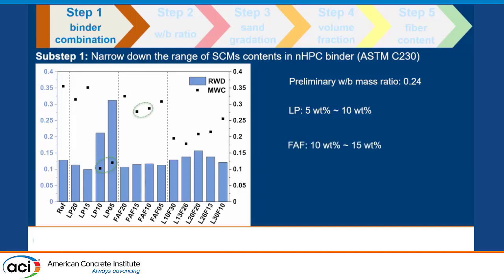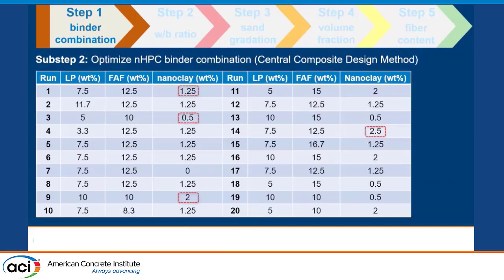Similarly, we can find the optimal range of Class F fly ash is 10 to 15%, and in the ternary binder system, the results confirm that the limestone powder content should be less than or equal to the fly ash. And the preliminary range for the nano-clay is from 0 to 2.5%. Now we can optimize our binder by the central composite design method. As you can see, we have 20 runs in this table, with 5 nano-clay contents.